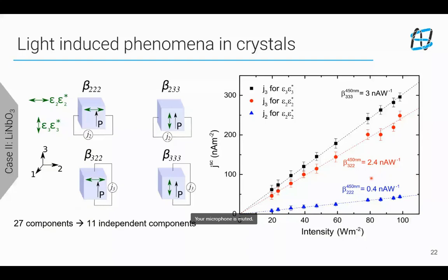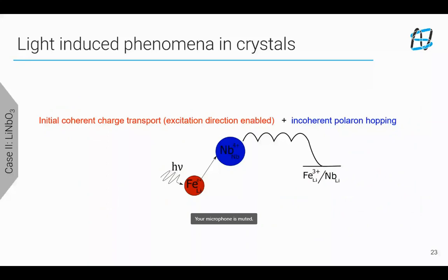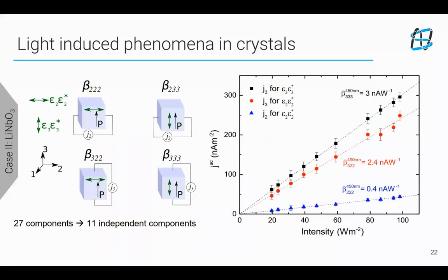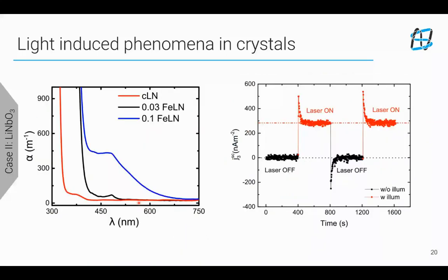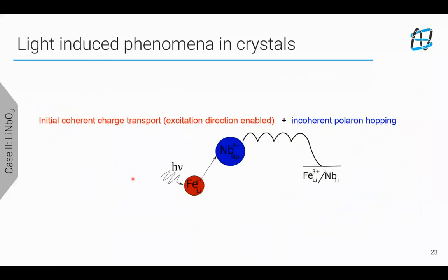So then we discussed what is really happening. Of course, it's typical of a crystal that when you shine light onto it, from the absorption spectra previously, we realized that with the incorporation of iron, the absorption has increased. So you know that the initial excitation, especially at this wavelength, is due to the iron incorporation in lithium niobate. So we said, okay, when we're shining a light onto the crystal, the iron ion, which is sitting in the lithium site because of its defect incorporation, is excited and gives an electron to the niobium atom, which is basically forming the conduction band in the crystal.